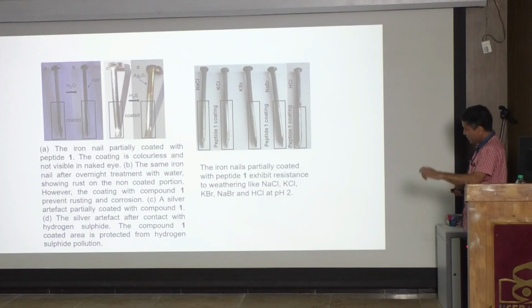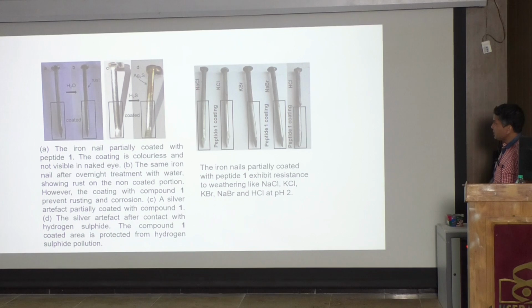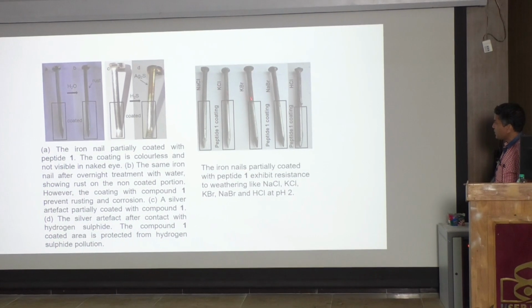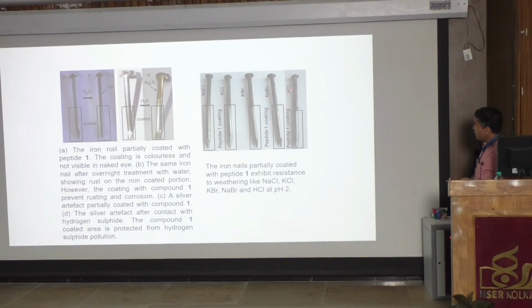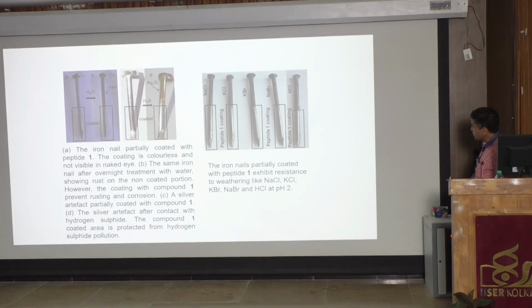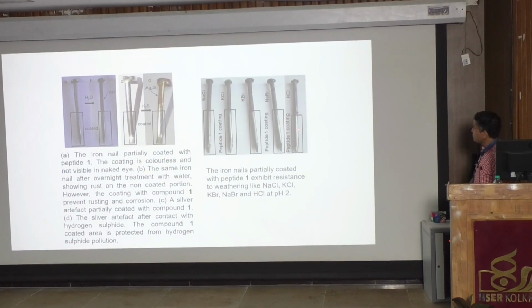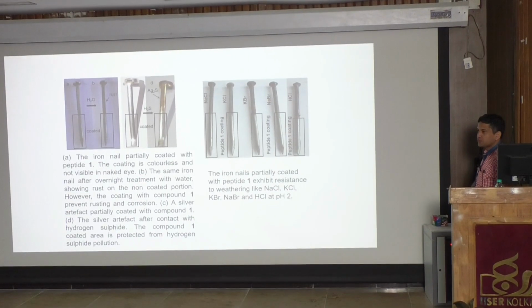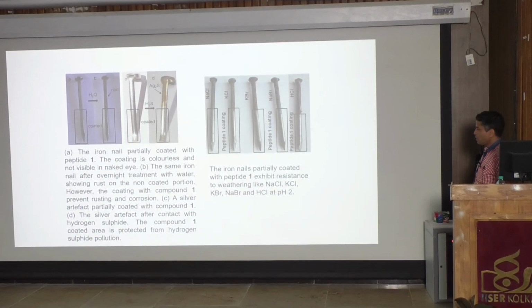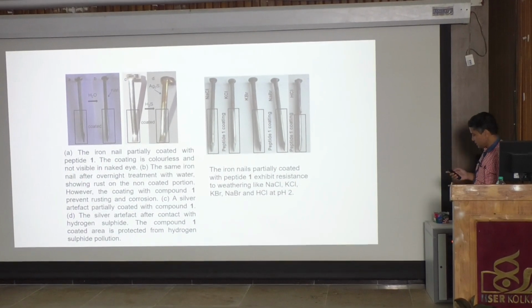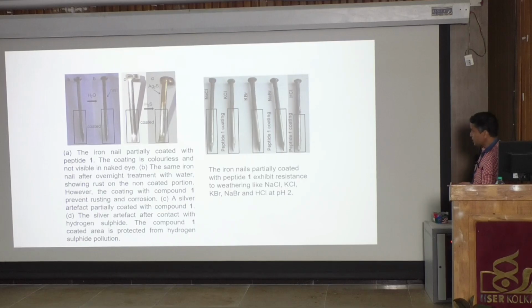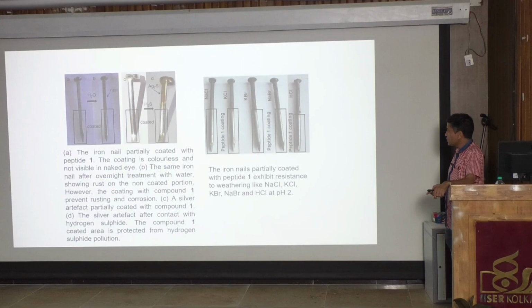We have even tried it in very harsh conditions. We put it in sodium chloride, potassium bromide, sodium, even in HCl. When it is coated, there is no corrosion with HCl, but the uncoated part is corroded by HCl. So we think this compound is very effective to protect materials from corrosion.